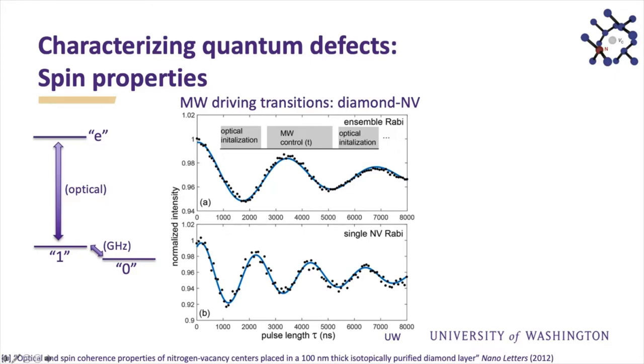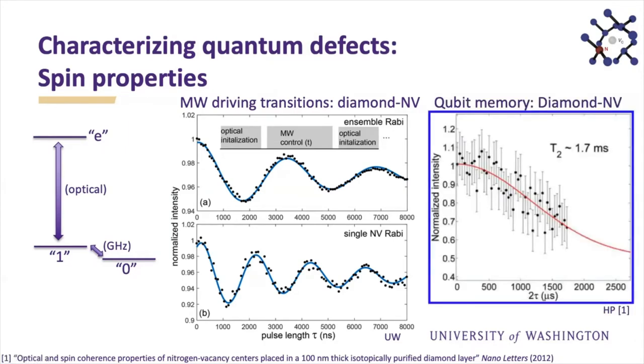So this is an ensemble of many, many centers in a diamond sample. And then here you can see the similar measurement done of driving or creating this qubit state in different superpositions for a single nitrogen vacancy center. So if you wanted to have the qubit state where there's half probability in zero and half probability in one, you would stop your drive right about here. All right, and so then what you can do next is, once you stop that drive here, you can measure how long it takes to decay. And this is an example decay curve of measuring that lifetime. And this is done at room temperature for the nitrogen vacancy center in diamond, and the T2, or the quantum memory time, for this particular NV center in this particular sample is around 2 milliseconds.